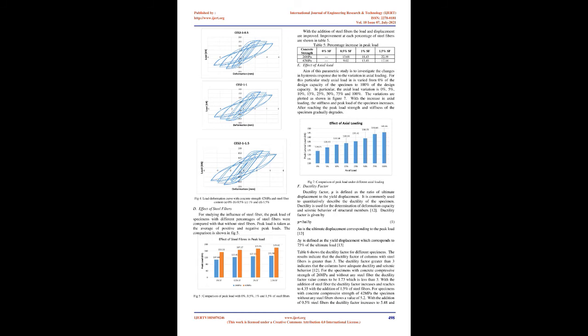E. Effect of axial load. The aim of this parametric study is to investigate the changes in hysteresis response due to the variation in axial loading. For this particular study, axial load is varied from 0% of the design capacity of the specimen to 100% of the design capacity. In particular, the axial load variation is 0%, 5%, 10%, 15%, 25%, 50%, 75%, and 100%. The variations are plotted as shown in Figure 7. With the increase in axial loading, the stiffness and peak load of the specimen increases. After reaching the peak load, strength and stiffness of the specimen gradually degrade.